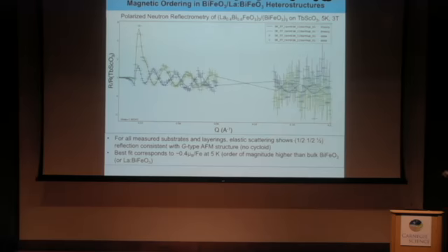So this is one of our films. So this is a 3-repeat film now. And I should note that the TEM of this film shows actually that we get an anti-ferroelectric pattern throughout the entire film, which maybe is unsurprising because there should be some crossover regime where they're coupled. And this is actually a composition that is in the morphotropic phase boundary, despite still seeing clear segregation where the bismuth ferrite is bismuth ferrite and lanthanum bismuth ferrite is lanthanum bismuth ferrite. But if you average over the whole system, you're in the morphotropic phase boundary, which is kind of what's always going to happen for these 40% lanthanum films with 50-50 superlattice ordering.